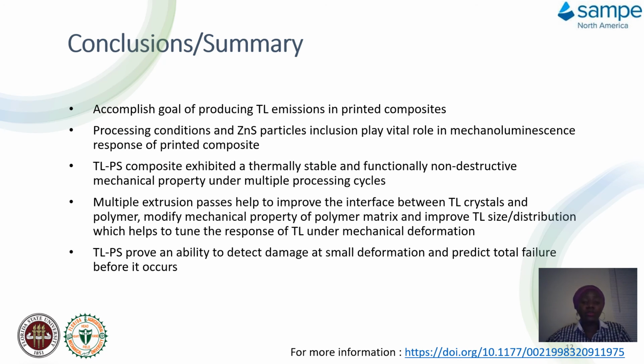So in conclusion, we were able to achieve our goal, which is the inclusion of the TL emission in the printed composite, and also we were able to understand the processing condition on zinc sulfide particles, which shows it has a vital role in allowing the mechanoluminescence response on the printed composite. And we also achieved a better thermally stable material without destroying the zinc sulfide, which is a non-destructive mechanical property after exhibiting multiple extrusion cycles.